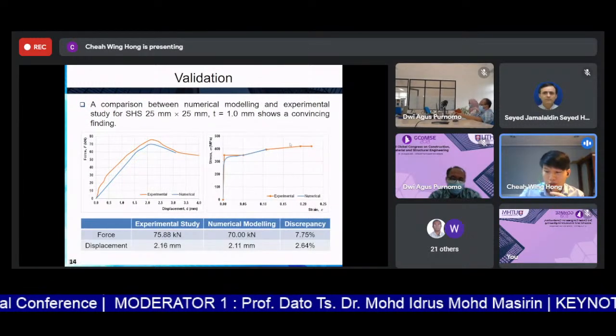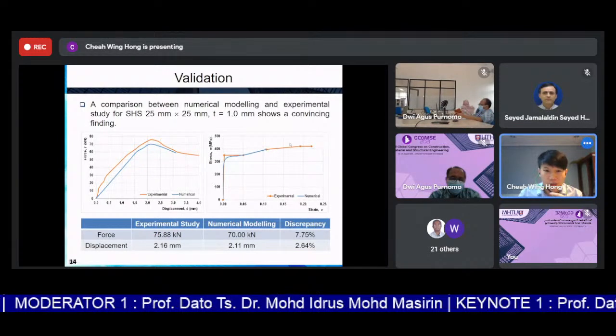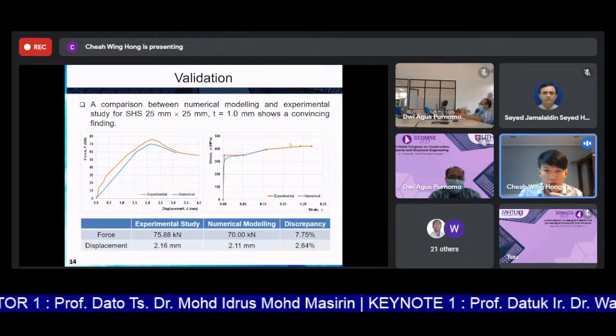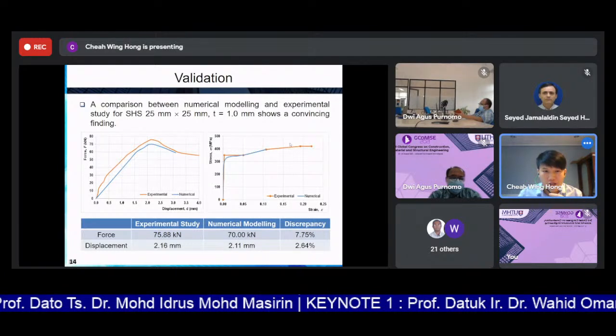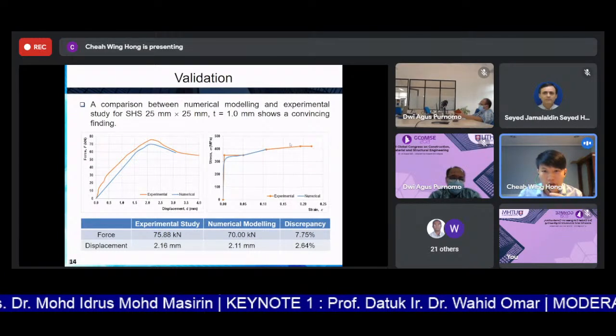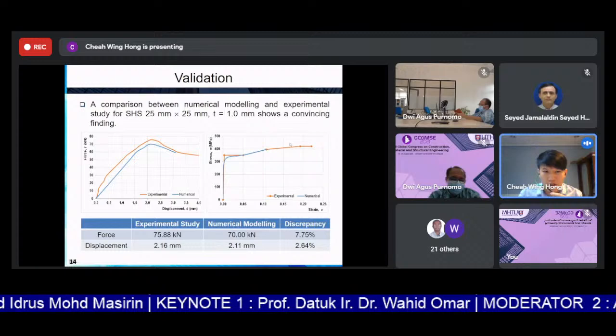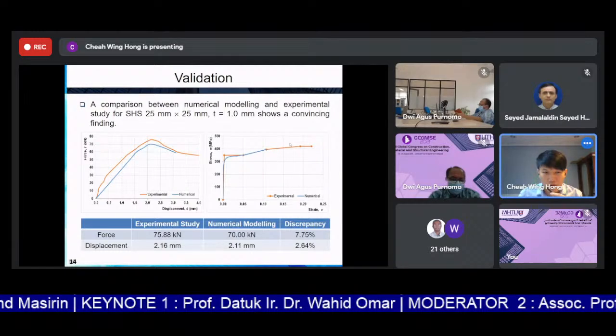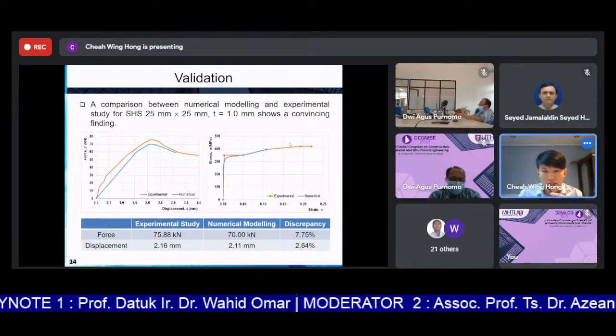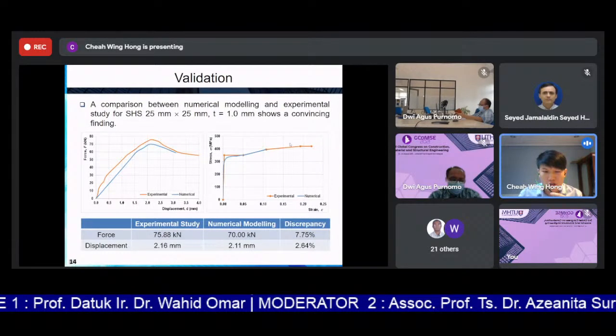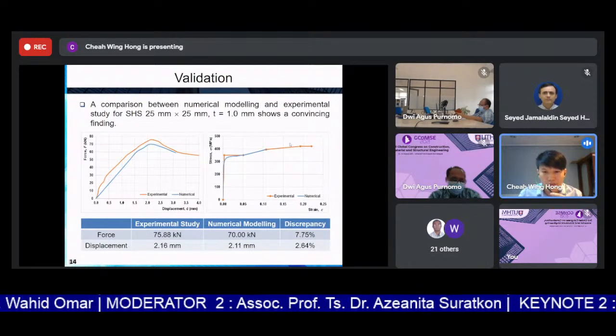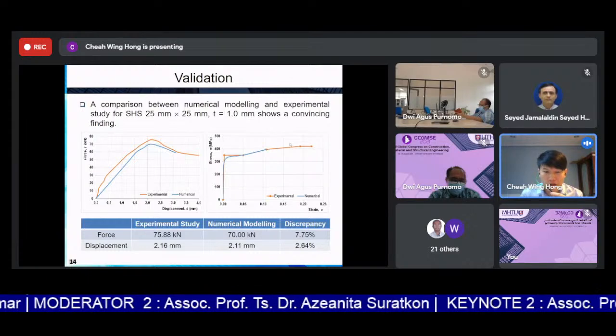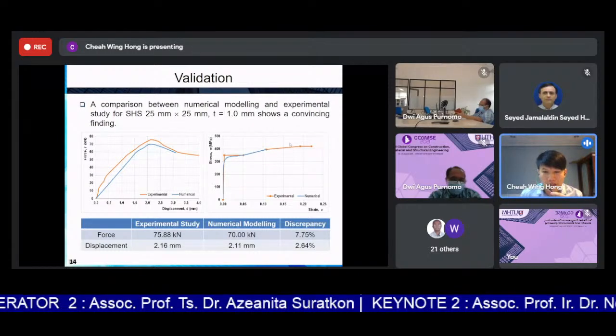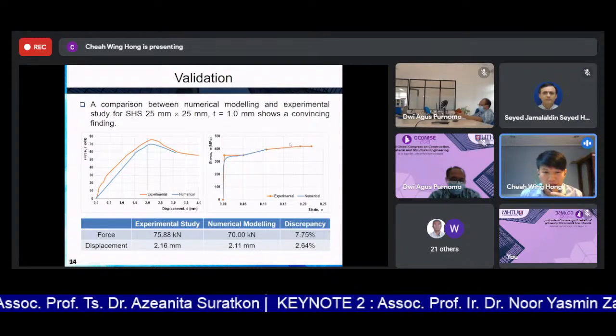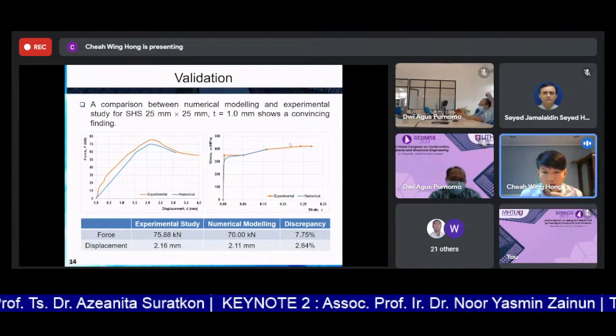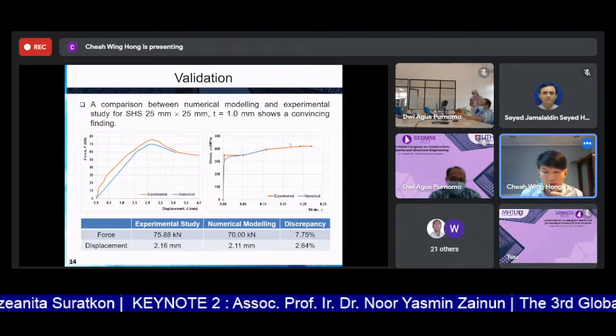Next, the validation is done to ensure that our numerical modeling will produce convincing results. A comparison between the numerical modeling and the experimental study for the SHS 25 millimeter times 25 millimeter with a thickness of 1 mm was done, and it shows quite convincing findings, where the discrepancy between the force for the numerical modeling and the experimental study is about 7.75%, and the displacement is about 2.64%, which is within the range that we can accept.